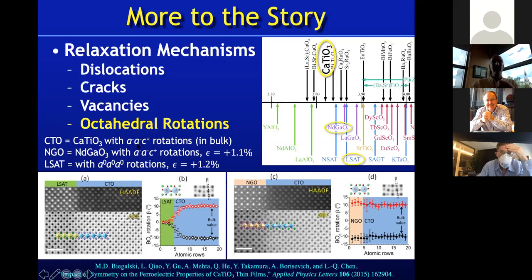In bulk calcium titanate, the orthorhombic Pnma rotation sequence is an out-of-plane rotation along the a-axis, an out-of-plane rotation along the b-axis, and an in-plane rotation along the c-axis. This notation I know you learned about from Professor George last week. So let's see what happens in reality, and that is shown here. Hopefully you can see by eye that at first there's very little, it follows the rotational pattern of the substrate, but then over time it reaches a steady state value, which is what's called the bulk value.